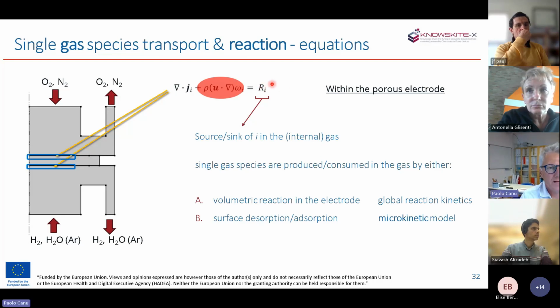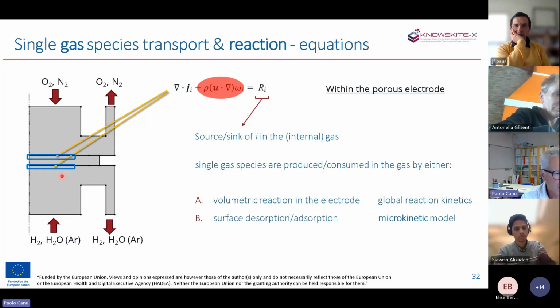On the reaction contribution of single species within the electrode, we should account for any path where oxygen on the cathode side or hydrogen and steam on the anode side can be consumed or produced. Now there are two approaches. One is a simpler one, where within the electrode we expect a consumption of oxygen on the cathode side, hydrogen on the anode side, through a reaction taking place uniformly within the electrode. That is essentially based on a global electrochemical reaction, and the rate is described by some simple expression like Butler-Volmer.